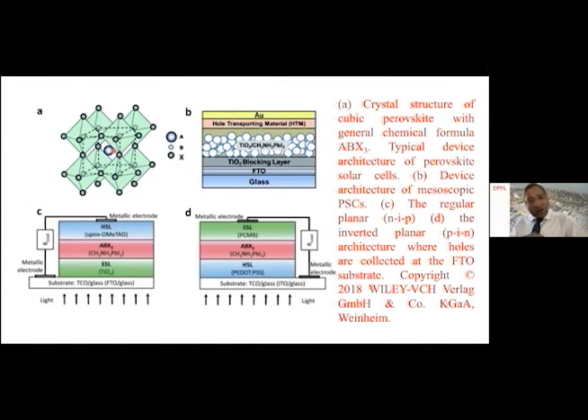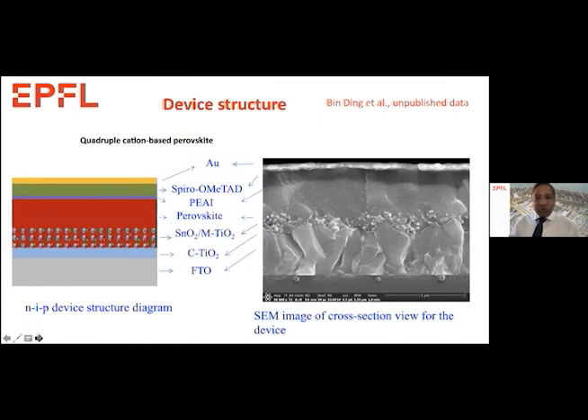Now you will see in a couple of slides later what a two-dimensional perovskite is. Before I jump onto that, remember that we are depositing a two-dimensional perovskite on top of the three-dimensional perovskite, a very thin layer, which is not visible, but you will see in the spectroscopic characterization how significant the characterization techniques are. Then we have the hole transporting material and then gold as a contact. So this is typically a NIP configuration as shown here.